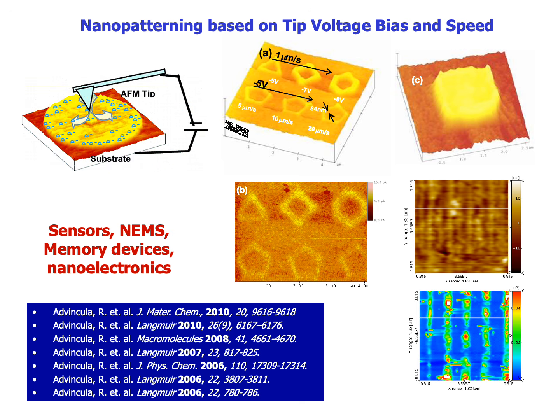where patterns can be made with high resolution all the way to less than 100 nanometers. This approach actually resulted in the ability to control these pattern features based on the amount of voltage applied, the residence time of the tip or current, as well as the thickness and properties of the film for cross-linking. So in this case, we were able to develop devices for sensors, memory devices, demonstrate nanoelectronics, and NEMS.